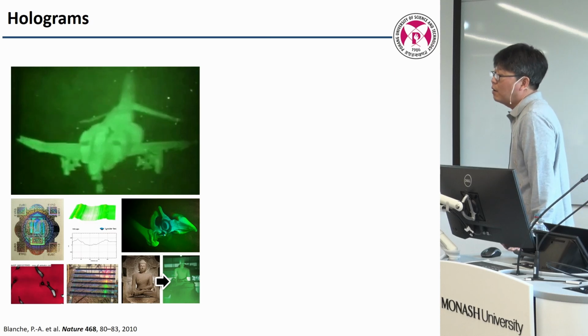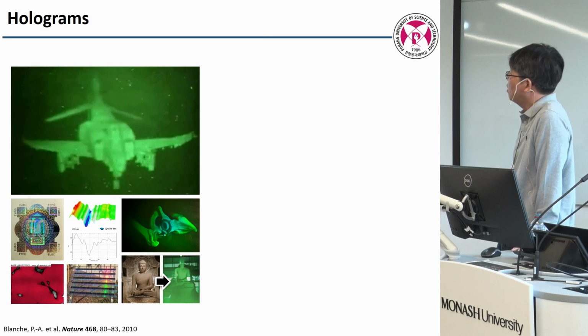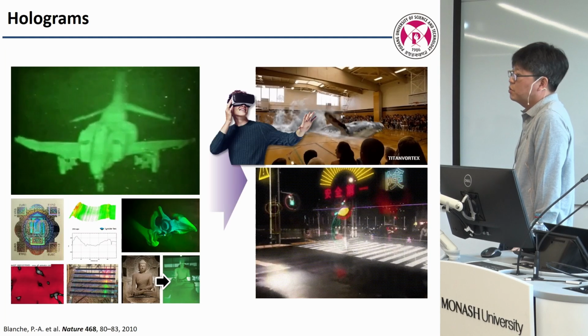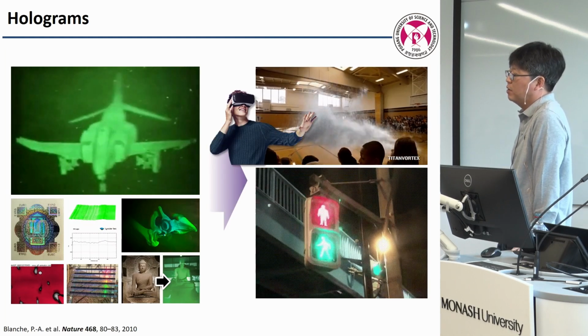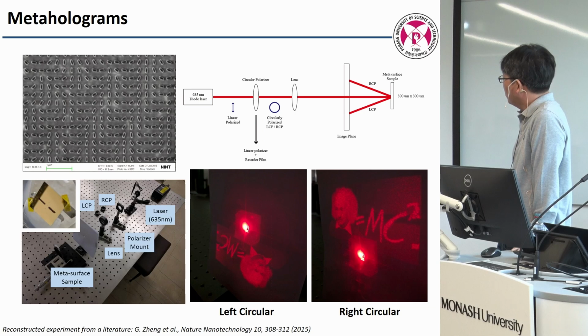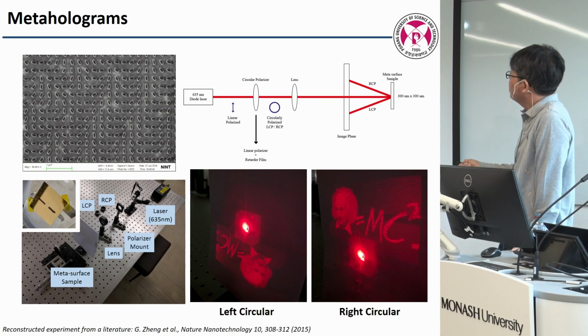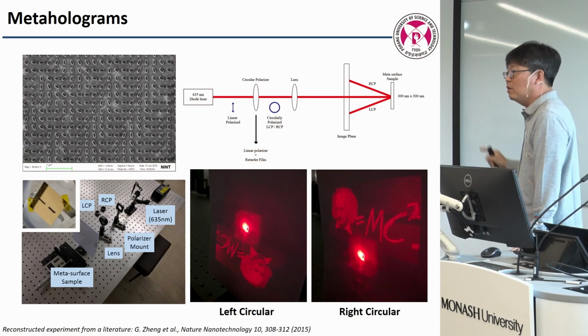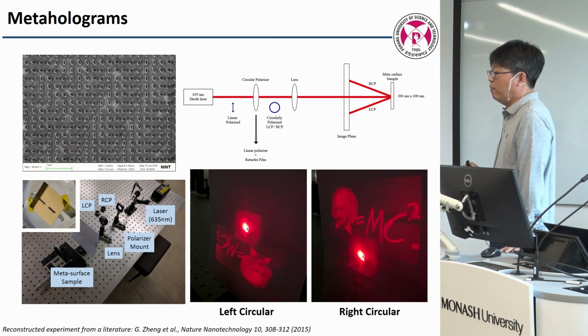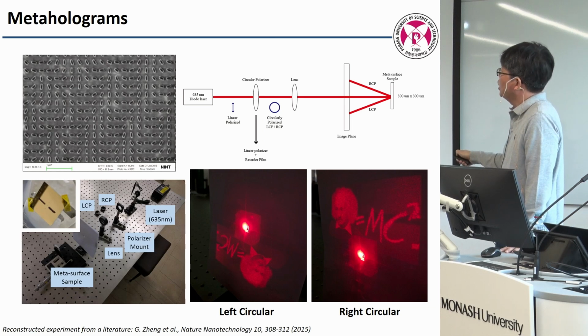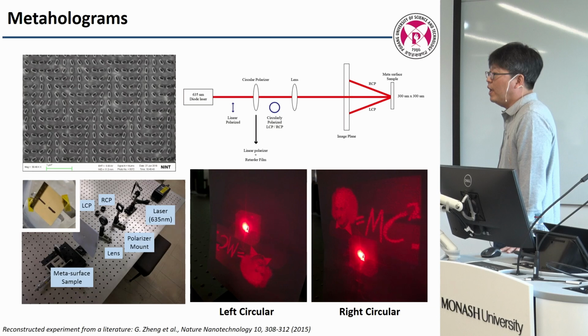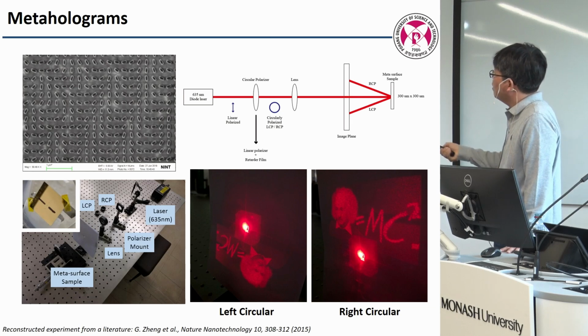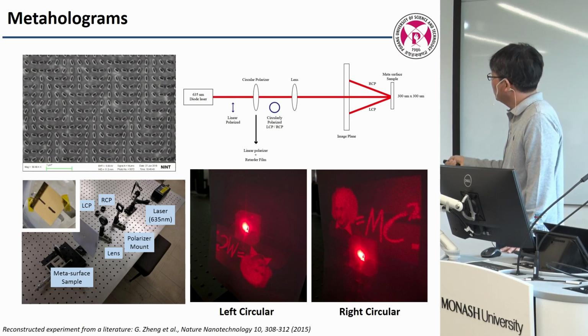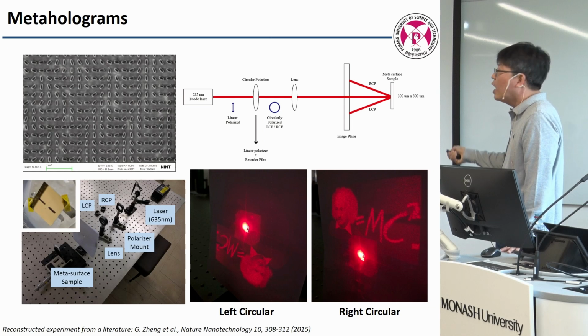So for a few minutes, I'll talk very briefly about hologram. Hologram is control of the phase information of the light. So this is a famous work from Thomas Zentgraf in Germany. They use a gold nanorod and change the angle. This rotation angle is related to geometric phase control. So a rotation of theta makes a 2 theta phase difference. But anyway, you shine the light here, apply circularly polarized light, and you will see a very high resolution image.